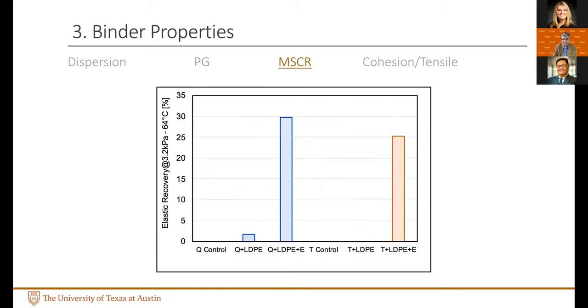MSCR, the same thing, you see stiffness increase, and elastic recovery. Really, none of these materials showed any elastic recovery. The reason why you see an elastic recovery here is because we added an elastomer, the terpolymer, to the mix, and the elastic recovery that you see from this comes from that polymer.